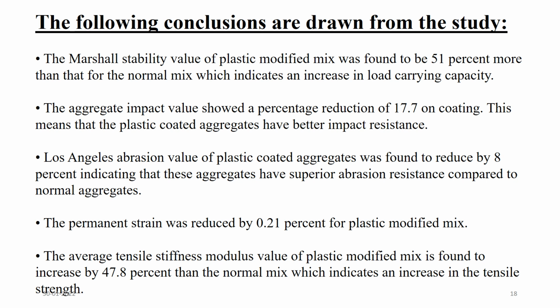The permanent strain was reduced by 0.21% for the plastic modified mix. The average tensile stiffness modulus value of the plastic modified mix is found to increase by 47.8% compared to the normal mix, which indicates an increase in tensile strength.